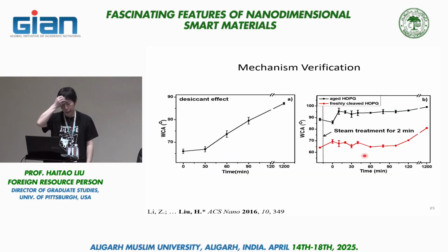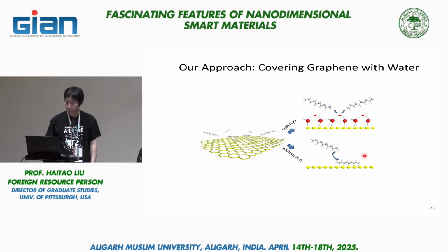Later we also did measurement using FTIR technique and showing that there is actually a very strong indication of hydrogen bonded water network on the surface. And even more surprisingly, this hydrogen bonded water network seems to be stable. So once they are formed, this seems to be stable even in much lower relative humidity, suggesting that there seems to be a lot of hysteresis of formation and disruption of the hydrogen bonded water network.